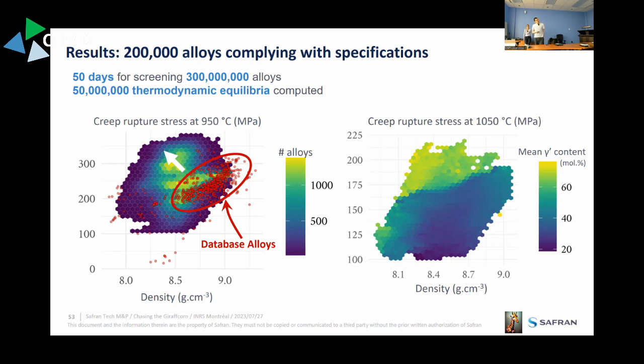The graph on the right shows the creep rupture at another temperature of interest, and the density as well. But now the color is the mean gamma prime content of each alloy. The gamma prime phase is what imparts the mechanical resistance. And I showed you before that the CALPHAD model and the Gaussian process model do not communicate with each other, so they can kind of diverge. But what is shown here is that, with a lot of alloys, you have representation effects and overplotting and a bit of a problem there. But most of the time you can find that the most resistant alloys are the ones containing the most gamma prime. And for two models that did not communicate, that's a good result, because it means that the physical prediction from the CALPHAD calculation correlates with the database approach, which is reassuring, which is not always the case.